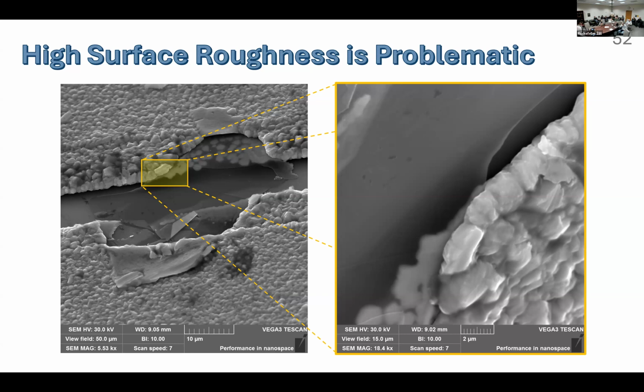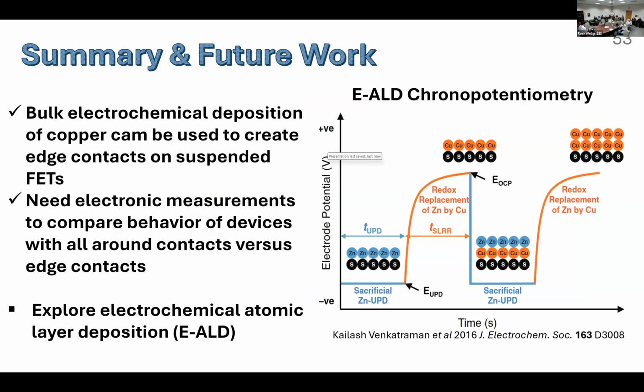So, because of the roughness, we want to explore other methods of doing this deposition, particularly electrochemical atomic layer deposition, in which you specifically use a sacrificial zinc layer to replace the zinc with copper in cycles. And this will ideally result in a monolayer growth of the copper on the edges of the MoS2 flake.